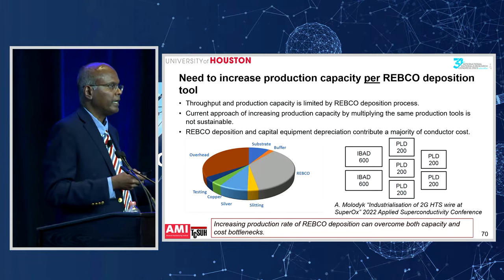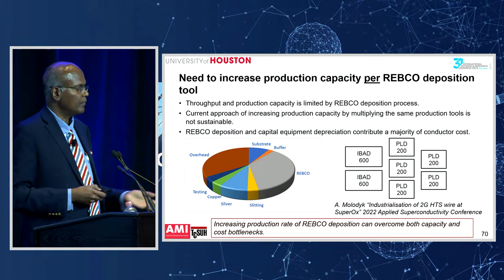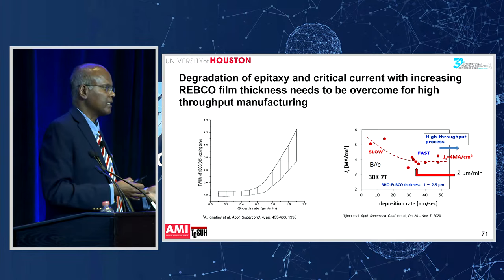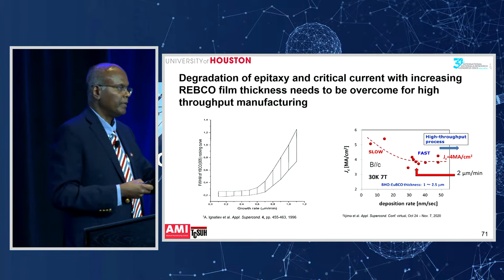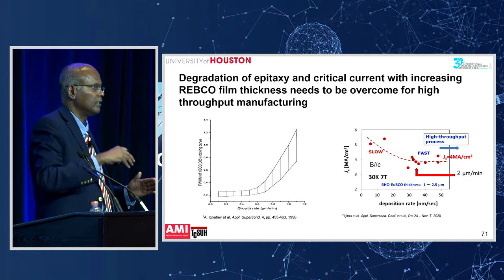So here's where, again, the material science comes in: how do you now do fast without degrading the epitaxy, right? On the left-hand side, I'm showing a chart of the texture. Remember, I showed the texture is very important for the superconducting film. You can see the texture is actually increasing, which means the epitaxy is really degrading as you grow faster, as you make the films faster, which is not unusual.